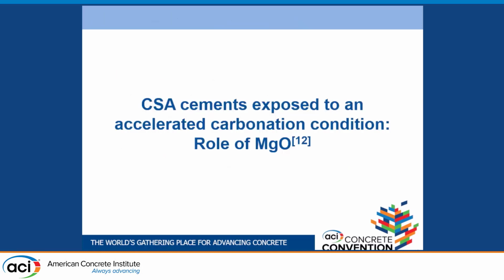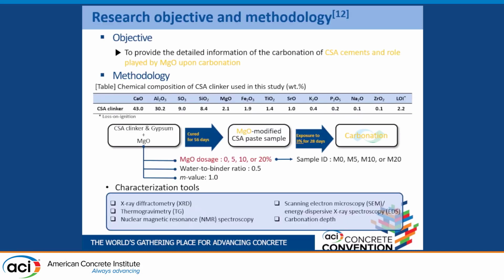So this experimental research mainly focused on providing detailed information about the carbonation behavior of CSA cement and the role played by magnesium oxide upon carbonation. CSA clinker and gypsum were used to compose the CSA cement, and then magnesium oxide was added to the sample at 0, 5, 10, and 20%. These samples were denoted M0, M5, M10, M20, respectively. These samples were sealed cured for 56 days, and then carbonated for 28 days at 3% CO2 concentration.